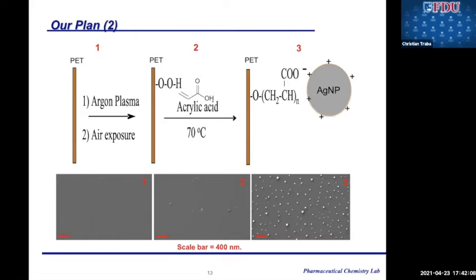The construction of anti-infection biomaterials essentially involved 3 steps. The first involves the treatment of either PET or silica wafers to 80 watts of argon plasma for 3 minutes. The second is the plasma-initiated surface polymerization reaction. And the third involves the immobilization of silver nanoparticles.